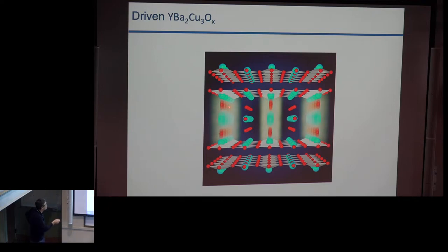And you know that at equilibrium the position of this apical oxygen correlates with superconductivity. In other words, you want the apical oxygen to be as far away as you can from the planes, so that this is a really very nice 3d x squared minus y squared orbital, and you have no 2p thing bothering you. But we're going to do the shaking, and this is going to be a periodic effect. So if you do this,